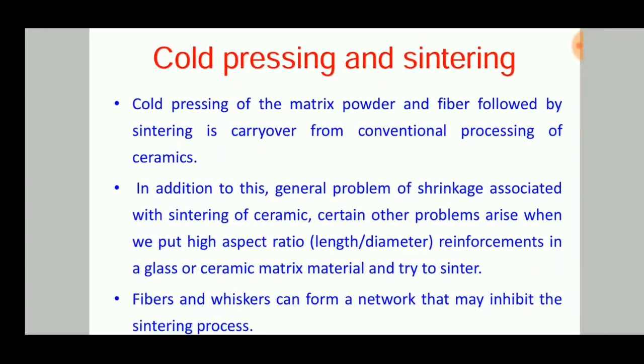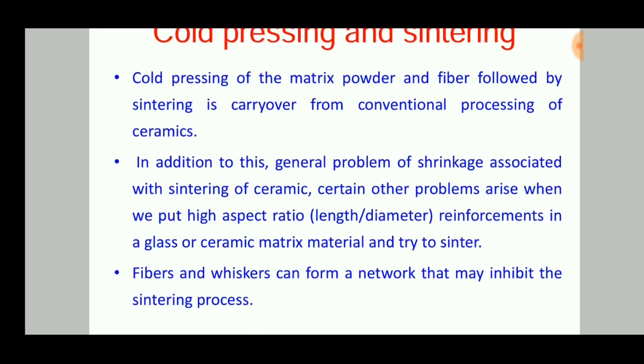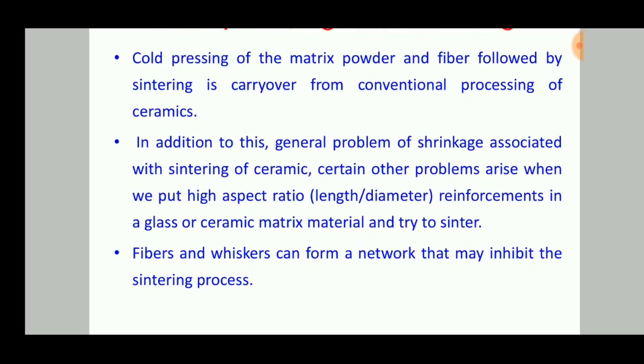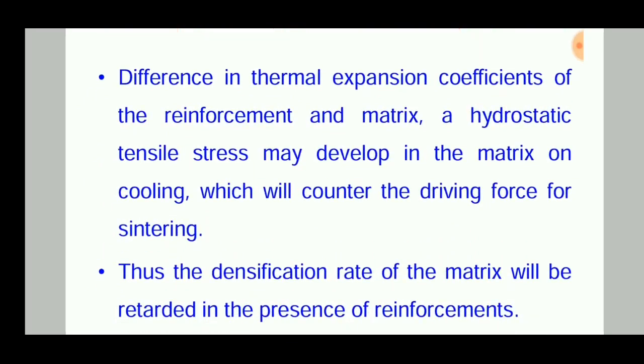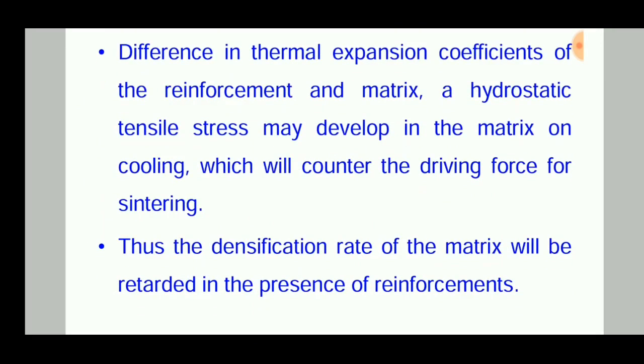Cold pressing of the matrix powder and fiber followed by sintering is carried over from conventional processing of ceramics. In addition to the general problem of shrinkage associated with sintering, other problems arise when high aspect ratio reinforcements — that is, high length-to-diameter ratio — are placed in a glass or ceramic matrix and sintered. The difference in thermal expansion coefficients of the reinforcement and matrix means a hydrostatic tensile stress may develop in the matrix on cooling, which will counter the driving force for sintering, thus retarding the densification rate of the matrix in the presence of reinforcement.